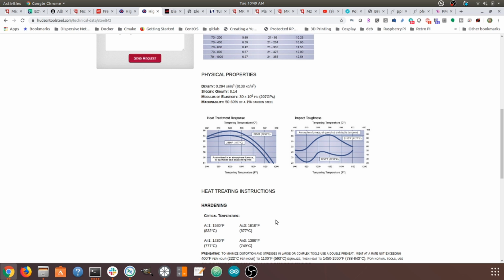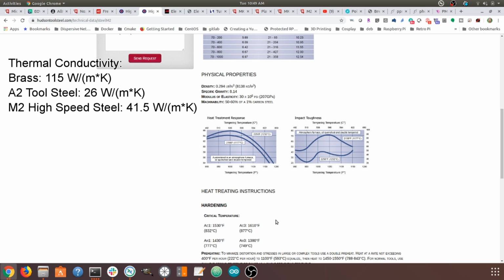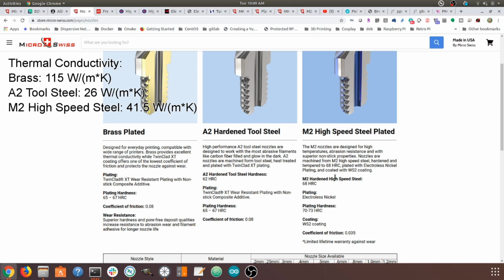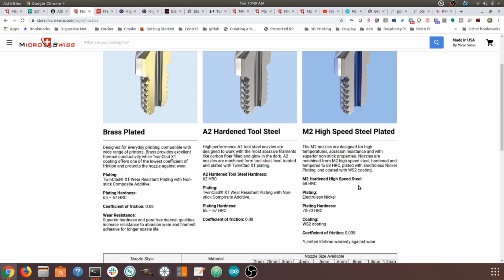And one thing, again, not on this page, it actually has a better thermal conductivity than that A2 hardened steel, with a thermal conductivity of 41.5 watts per meter Kelvin. Looking at our page here, that gives us a harder base material, a base material that has better thermal conductivity. And what they've done with this one is taken the plating and the coating a step further. They now have simply an electroless nickel plating applied to the outside. My guess is that is for both a little bit better friction as well as some better thermal conductivity.